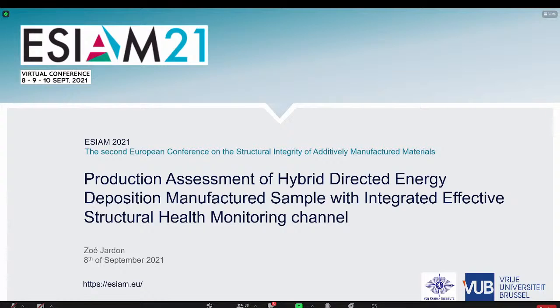Yeah, so indeed adding these open voids, these open cavities, in the parts is reducing the structural integrity of the part. That's why we try to minimize these capillaries. And we have done some testing on samples, some fatigue testing that showed us which diameters we need to reach to not influence the fatigue of the component. And mainly it's triggered by surface defects on the inner surface of the capillary. So the goal was here to see if the roughness that we get out of this hybrid production process is acceptable or not. And with the drilling operations, it showed that the fatigue is not affected for small diameters of the capillaries. This test campaign has been realized as a first step with capillaries of 3 millimeters.